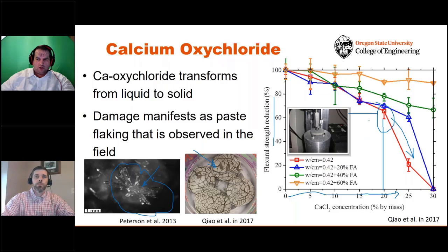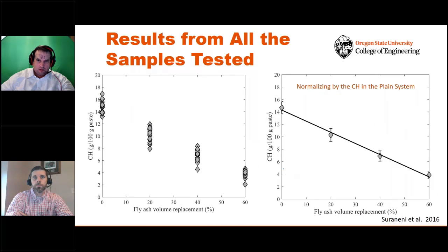One of the ways that you reduce this potential for damage, you use more and more fly ash, and the only thing you're going to see here is a little bit of dissolution that's happening in the overall system.